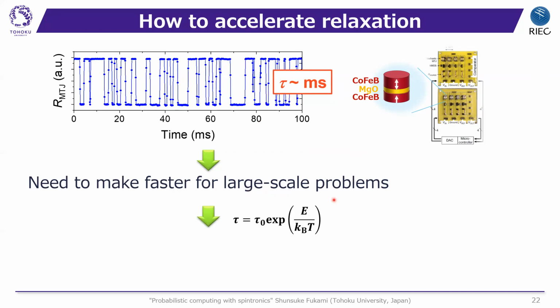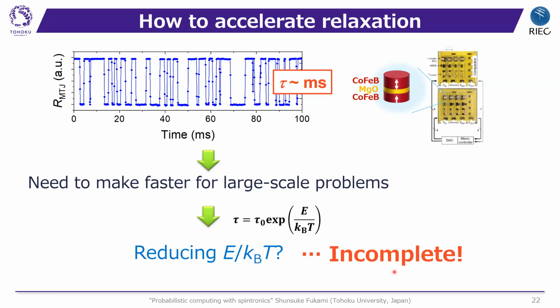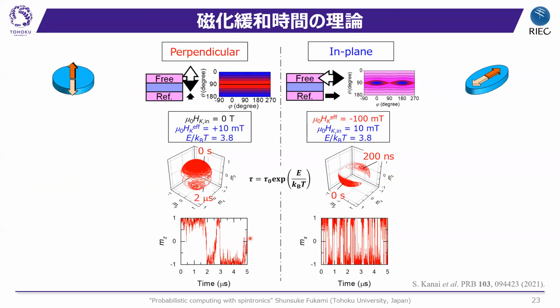And initially, we thought that reducing the relaxation time can be achieved by reducing the thermal stability factor E over kBT, but we found that this is not complete to reduce the retention time or relaxation time. So let me show our calculation results. We performed micromagnetic simulation for the perpendicular magnet and the in-plane magnet. And these two systems have an equal thermal stability factor of 3.8. So E over kBT is 3.8 for both systems.